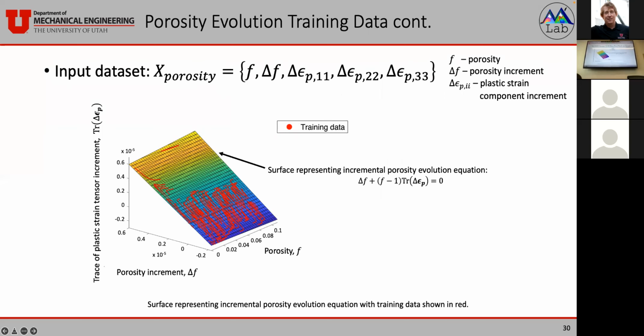I've shown the input data set for porosity evolution here, as well as the training data on the surface. And something to point out is that there are sparse regions on the surface. The reason for this is that we performed space filling on the yield surface. We didn't consider this in the space filling technique, so we might expect for some sparse regions to exist on the surface.